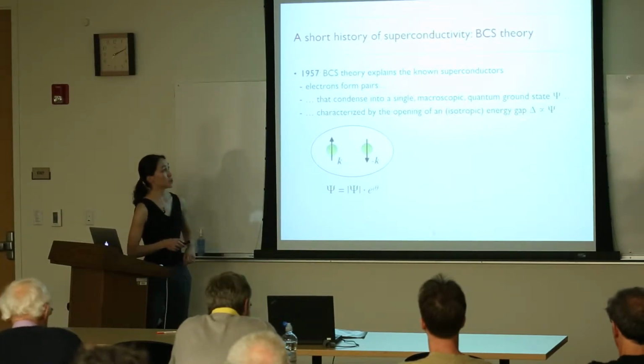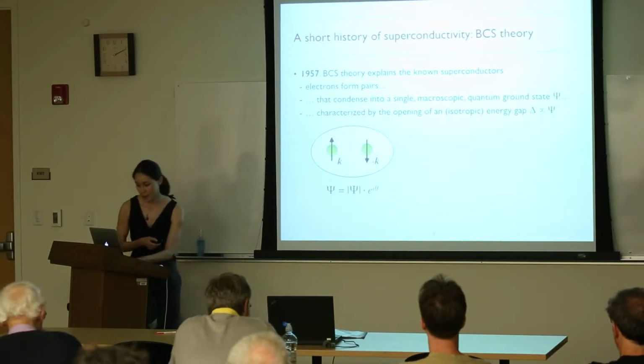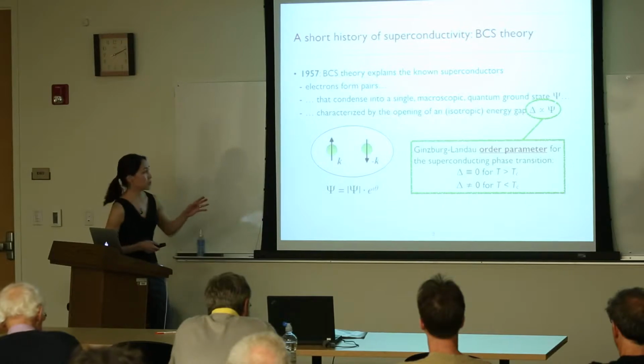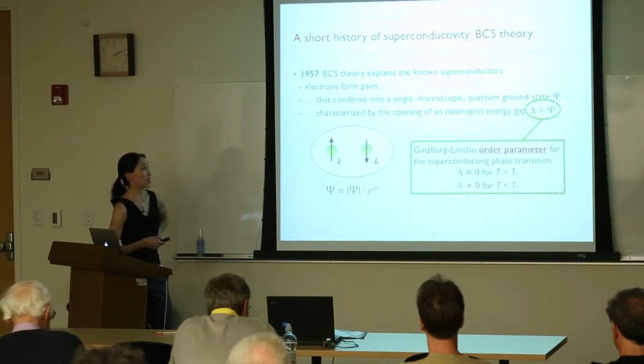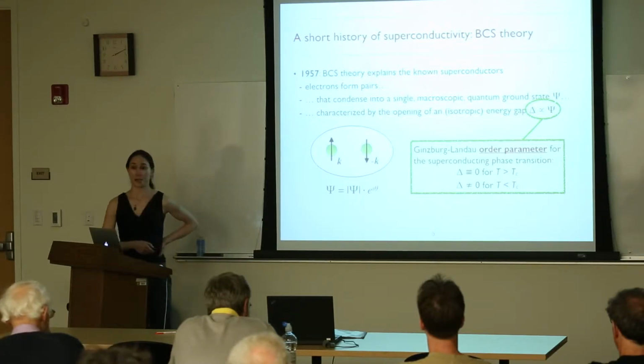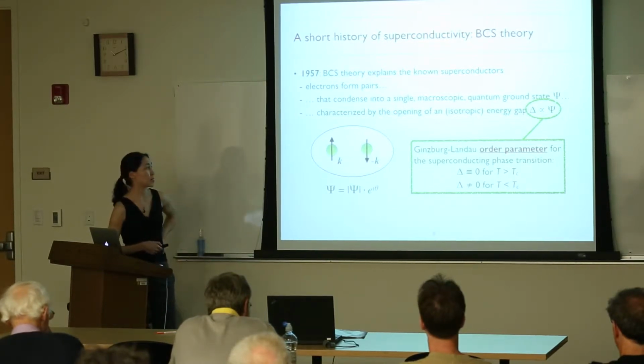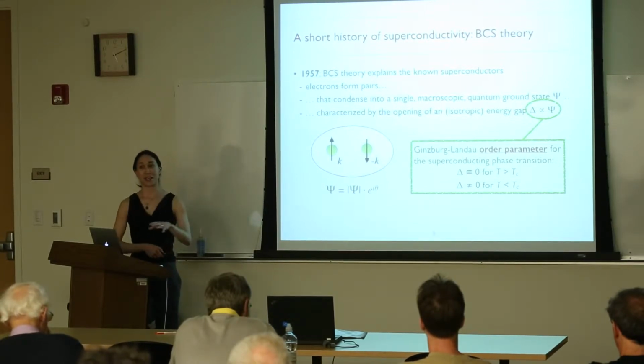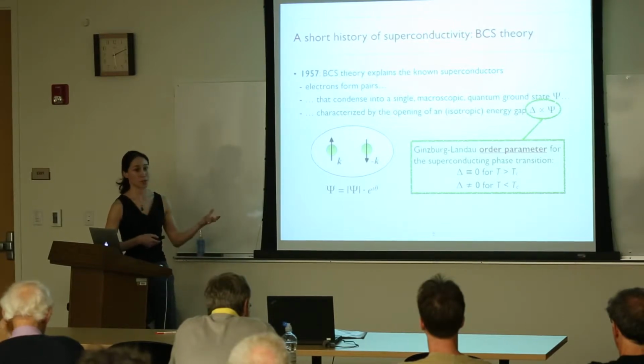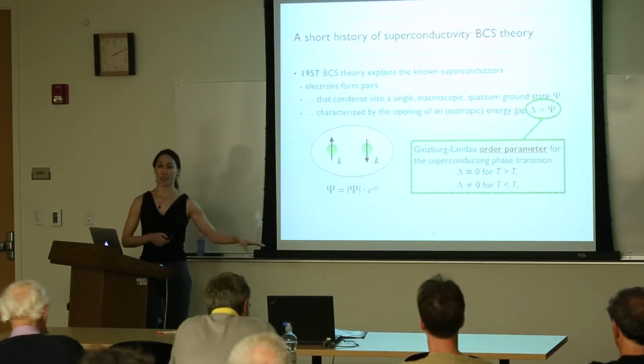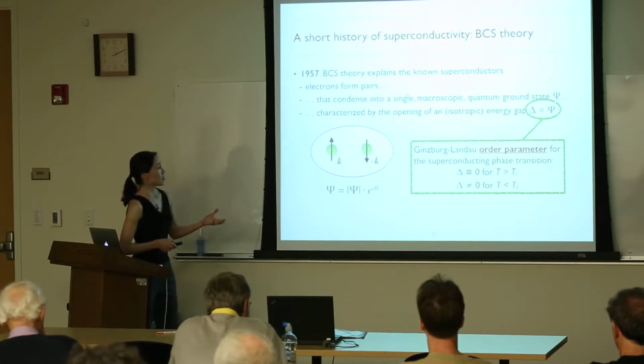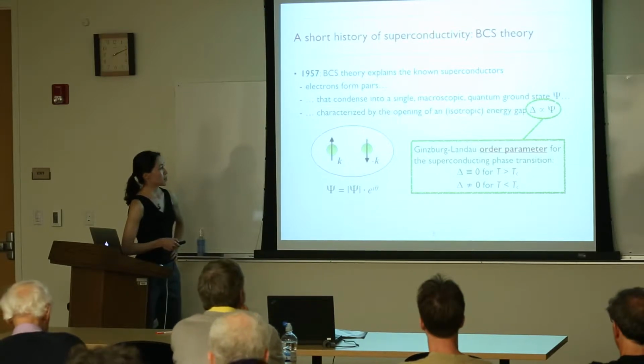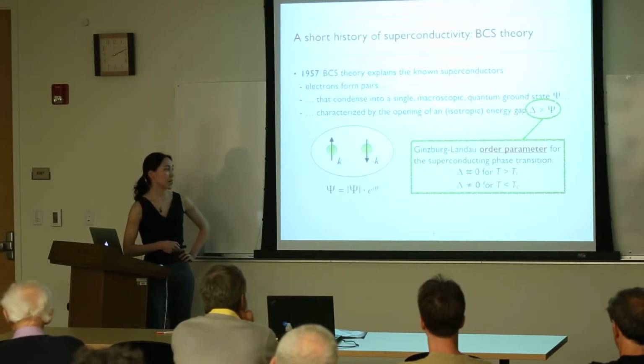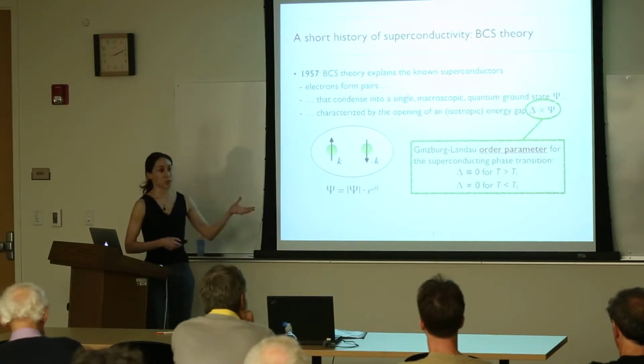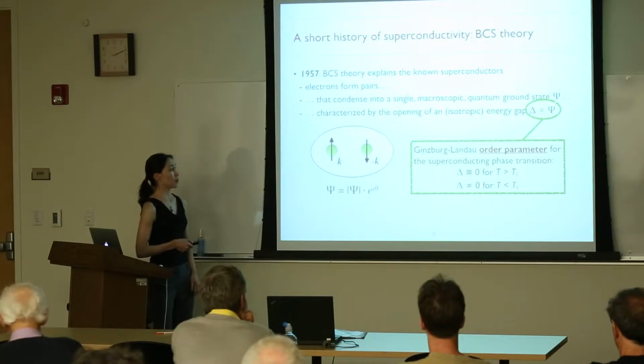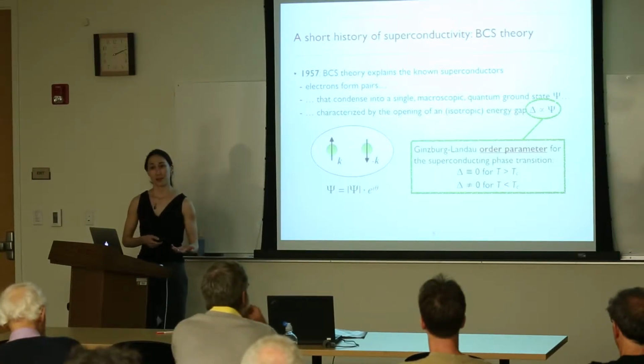It turns out that this gap is going to be proportional to this wave function psi. And to bring it one step further, because I'm going to be using this terminology a lot, both the gap and the pair wave function are also often referred to as the order parameter for superconductivity. And this goes back to Ginzburg-Landau theory. Those of you who don't know about that, don't worry. It's basically a phenomenological way to approach this kind of problem that ignores all of the microscopic details of what might be going on in these systems. The main idea is that you have some parameter that's identically zero above the transition temperature and then becomes non-zero below the transition temperature. So in the case of superconductivity, this quantity is the gap, and moreover, the gap contains some information about the superconducting state.